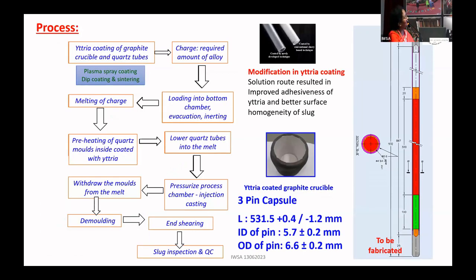So the process consists of this: yttria coated graphite crucible. You know yttria is the most stable oxide, which will not interact with uranium, plutonium, and zirconium. So you coat it with yttria. That has a technology again. Then you have a quartz tube which will be inserted at 1450 degrees, and internally, the 6 mm diameter should be coated with yttria. All the process has been done inside IGCAR only. Finally, you pressurize the injection chamber, you allow the melt to rise inside the quartz tube, and then you cut open to get the slug.